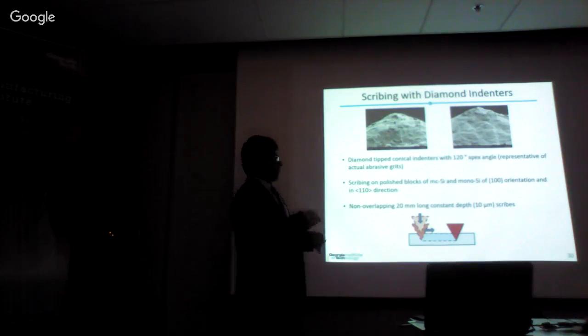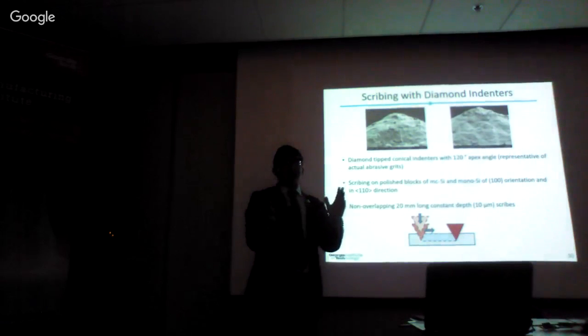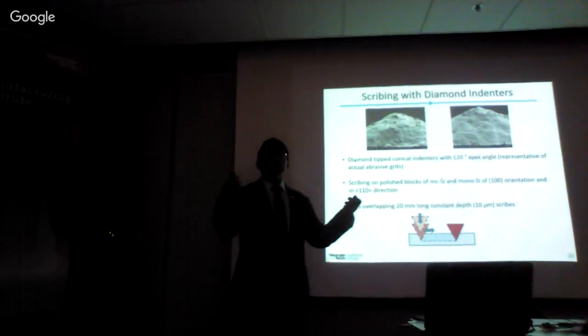Now, the scribes are made non-overlapping so that each scribe is identical in everything. We are just monitoring how much the material is wearing the abrasive at a constant depth of cut of 10 micron. What that means is we engage the indenter by 10 micron depth and then scribe for 20 millimeter. And we repeat the scribes many, many times and monitor at regular intervals, stopping the experiment for both mono and multi-crystalline silicon, and then checking the surface morphology of the diamond and the radius of curvature of the diamond, and how it is changing with wear.